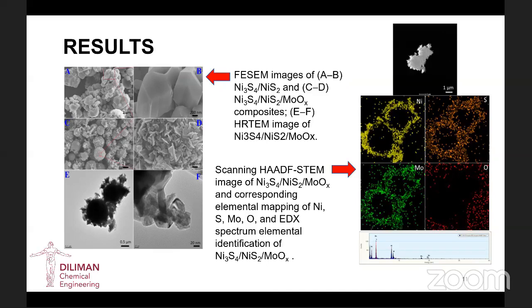Images E and F are the HRTEM images, and this clearly shows the nanosheets on the surface of the microspheres. And then on the right side, you have here what we call the high angle annular dark field imaging STEM, or scanning transmission electron microscopy image.